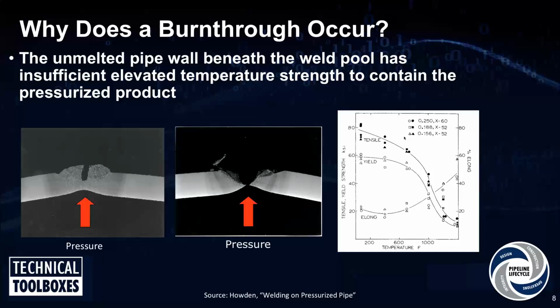So you kind of see that on the bottom left picture, that you have the weld pool, and directly underneath the weld pool you see kind of like a dimple in that pipe wall. And that's just the pipe wall locally yielding due to the stress of the pressure and the high temperature property of that steel being a reduced strength. So when a burn through occurs on in-service welding, what actually happens is a blowout. All right, so you want to go to the next slide?